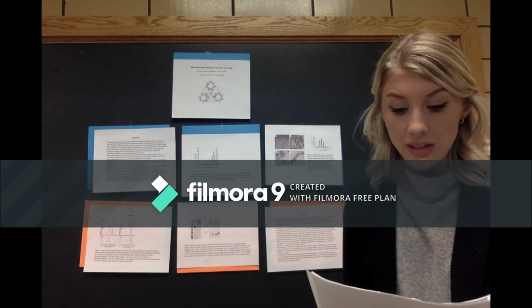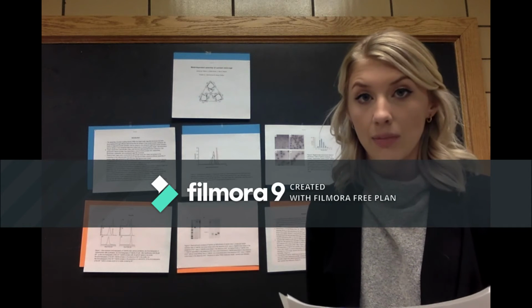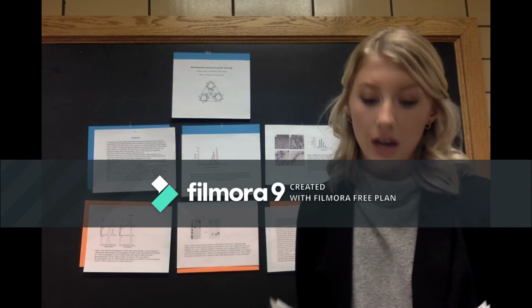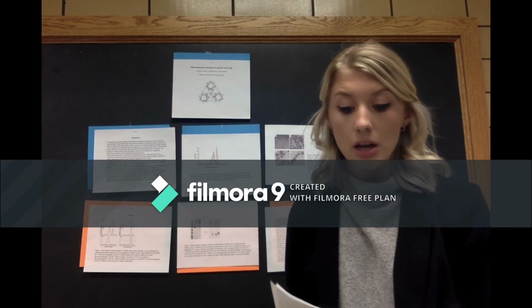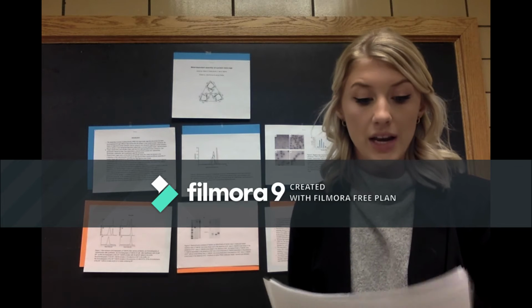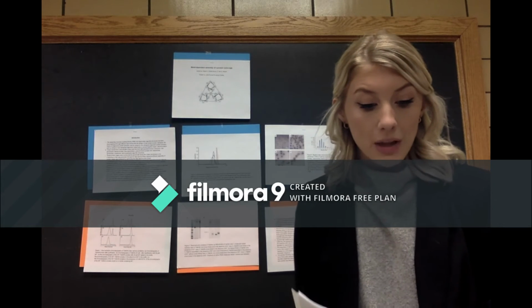In contrast, when the assembled species were re-chromatographed in buffer lacking the divalent metal ions, such as nickel, the protein eluted as a mixture of assembled and unassembled forms. Complete disassembly of the complex could be achieved by SEC in Tris-HCl buffer containing EDTA or with a buffer of pH 4.5.